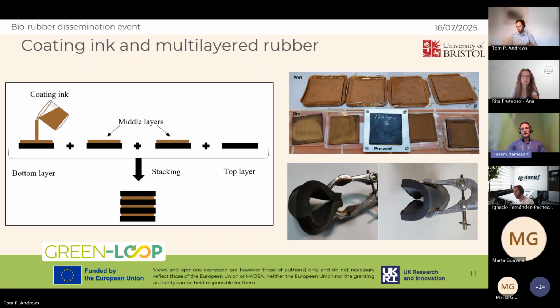For the next step in our research, we tried to find some application for the recycled rubbers, and we came up with the idea of a novel class of multi-layered coated recycled rubbers. So in the schematic, you can see that we have multiple rubber layers. These are recycled rubber layers that are coated using biodegradable and water-based coating based on lignin, sepiolite, and polyacrylic acid. These layers are coated on one side, stacked on top of each other, and then hot pressed at elevated temperatures to manufacture the final part.